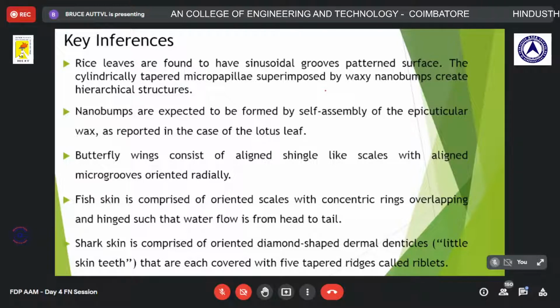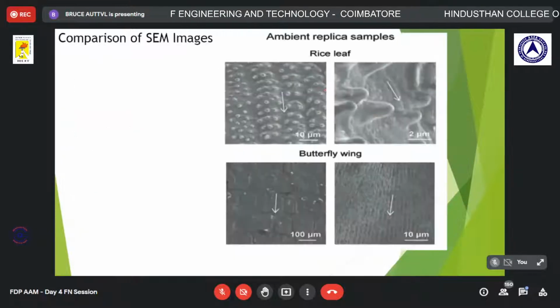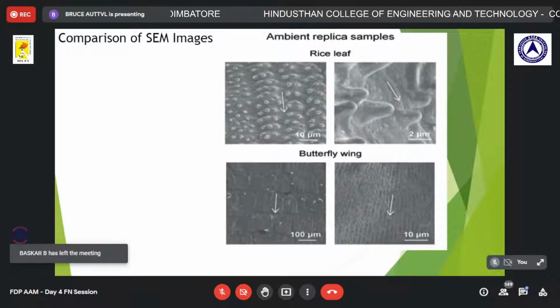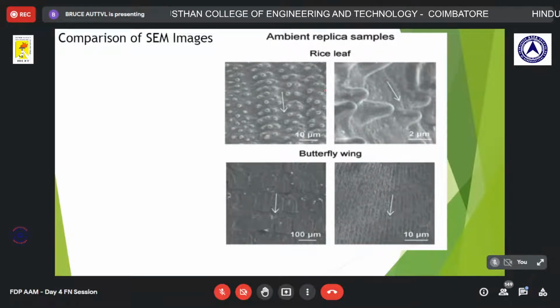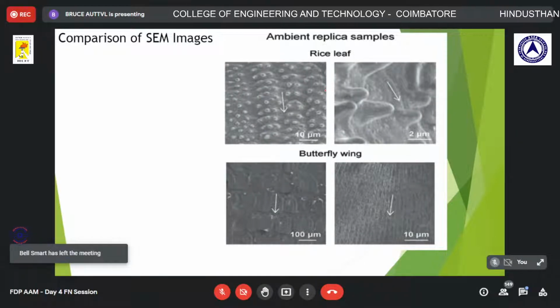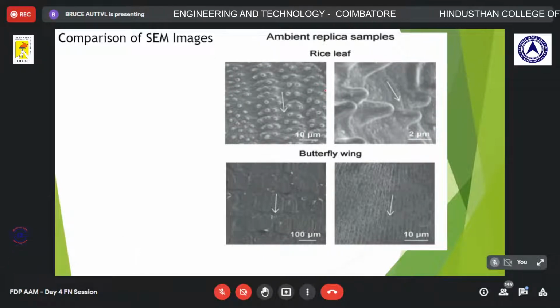And the same images I would like to present from the perspective of materials and characterization. The rice leaf, same image: here you can observe at 10 micrometer there are some spikes and valleys, and if you consider the 2 micrometer case, it is better visible. So in this way, significant hydrophobicity can be obtained. Once significant hydrophobicity is ensured, obviously we can achieve self-cleaning property, and we can achieve significant drag reduction, particularly in the case of ships. Okay, on the hulls and the different ship surfaces, if you are able to provide this kind of texture, hydrodynamic drag can be substantially reduced.